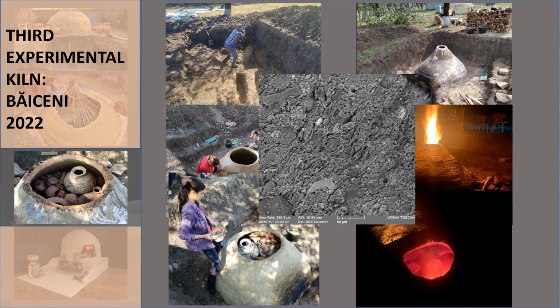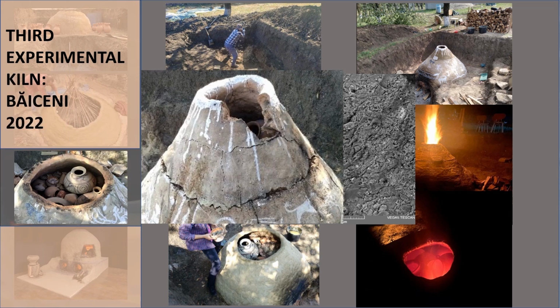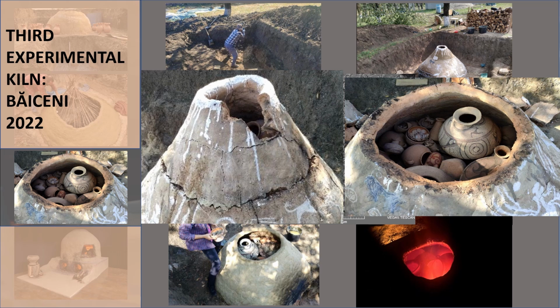By the end of the session, internal temperatures reached 850 to 900 degrees Celsius throughout the kiln chamber. Producing fully vitrified ceramics, the improved design resulted in stronger, more durable pottery, closely matching archaeological specimens.